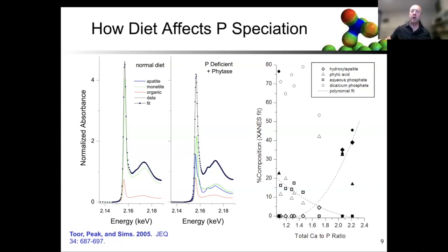And by doing that, you can kind of see from the left side here to the right that we shifted the type of calcium phosphate that formed into a much more crystalline phase. And then if you looked at the linear combination fitting, we also lost the adsorbed or aqueous phosphate. And so we've shifted the majority of the phosphorus in the system from something that's fairly soluble and fairly high risk to transport into a phase that's going to be stable when you put it out in the field. And so making those sort of observations with phosphorus XANES already gave us much better management outcomes.